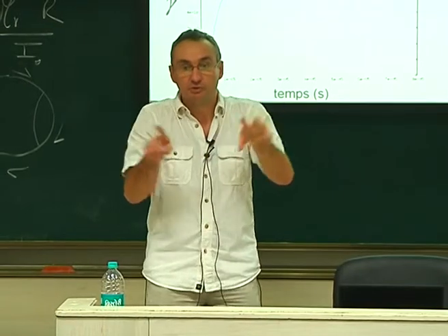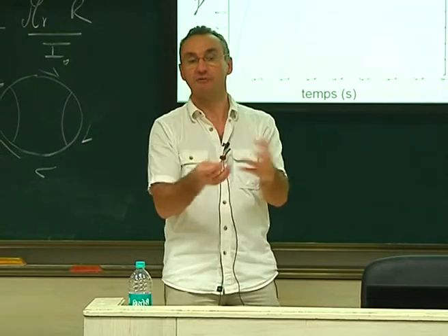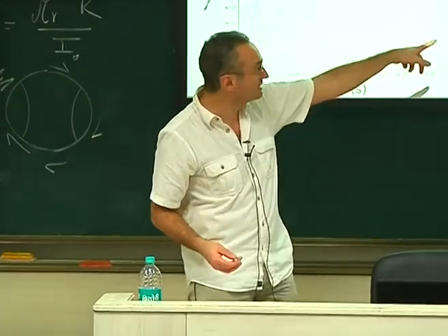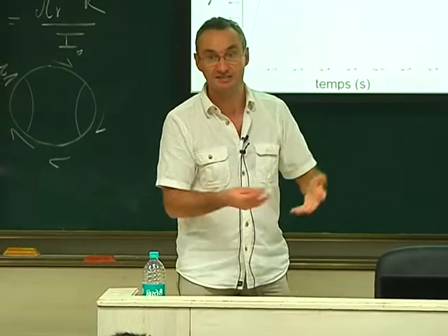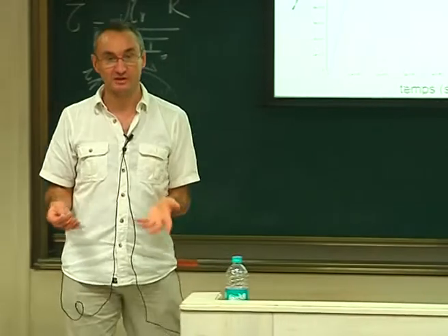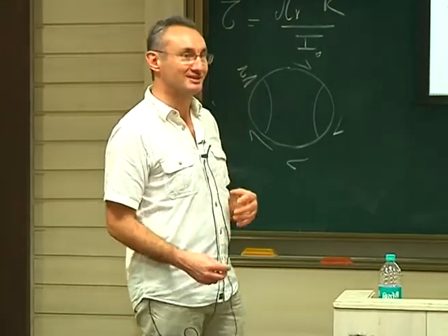denser and denser with the stress. But if it was annihilating, then you would have a constant flux of dislocation, and the density would not increase. Here you clearly see that the density increases with the torque, with the momentum. Okay? So there is no annihilation. So why is it so? I think Professor Rahman can help.